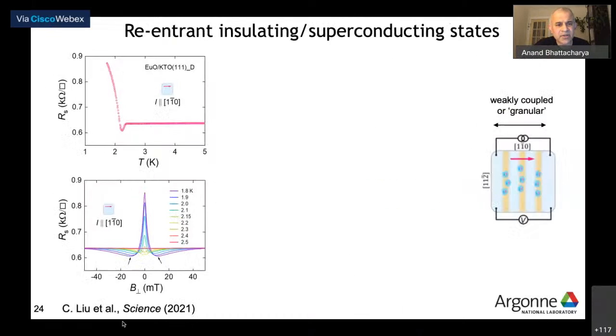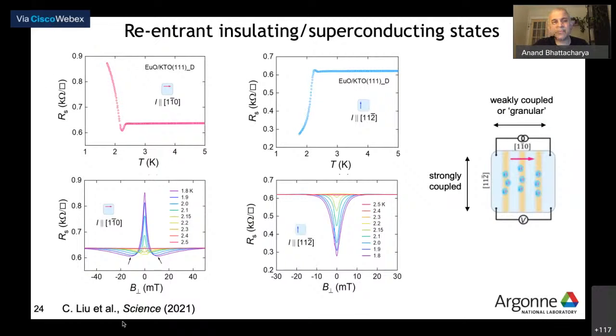One other thing that is very remarkable is that when you go close to the transition, for a fairly small magnetic field, the system has a very sharp response. Here I'm just showing you that rise along one direction. If you apply a magnetic field in that region, you find that the superconductor resistance just comes down right away, and then it settles down to the normal state value at higher fields. And for the feature that's turning down, a small magnetic field makes it rise and then settle down at a high magnetic field. We're talking about 100 Gauss levels, and it's enough to suppress these rising and falling features in superconductivity in our samples.